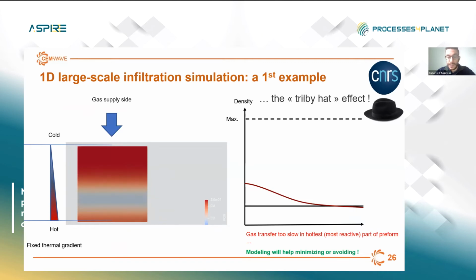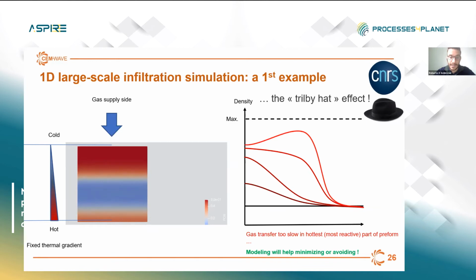What appears immediately, confirming the importance of controlling the temperature gradient throughout the preform, is what Professor Vignolz defined as the Trilby hat effect, which means that at the beginning we start from a good thermal gradient, but after a few iterations, the deposition stopped in the hottest part. So we couldn't reach the decrease of the porosity up to 0 value as we desired, since the gas get depleted. And this is something that we would like to quantify in the framework of the project, since it could be avoided by precise numerical modeling.